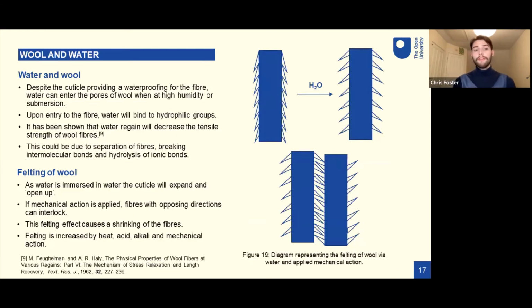So moving on from how wool ages, and more specifically to how wool interacts with water, I thought this was important to mention. As in conservation, it may be required to do some wet cleaning and also monitor the humidity. So this cuticle layer, although it provides a waterproofing, there are instances when water can actually enter the pores of wool. For example, at high humidity, or when the wool is immersed in water. You could also get this if there's damage to the cuticle.